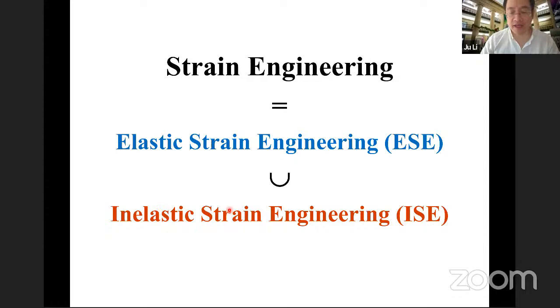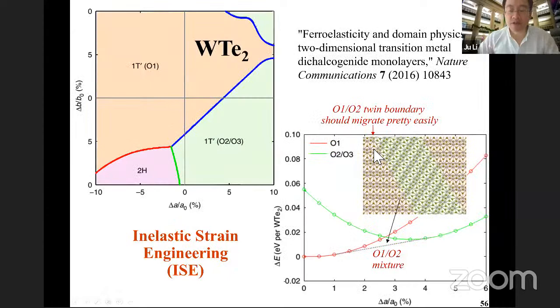One example is in this 2D material, for example, where most people talk about this 2H phase. This is like an HCP material where you have mirror symmetry but not inversion symmetry. But there is also something called a T phase, which is like the face-centered cubic structure in 3D, but now it's in 2D, where you have inversion symmetry but not mirror symmetry. What we have done, this is with my student Wenbin Li, is to show that this T phase actually is not stable, and it reconstructs into this 1T prime reconstructed phase.